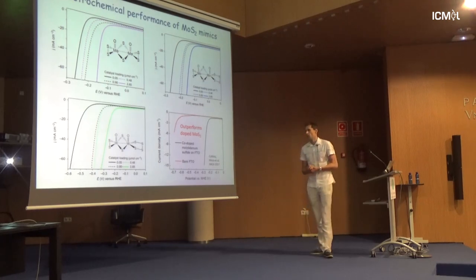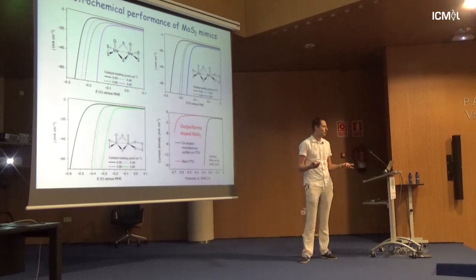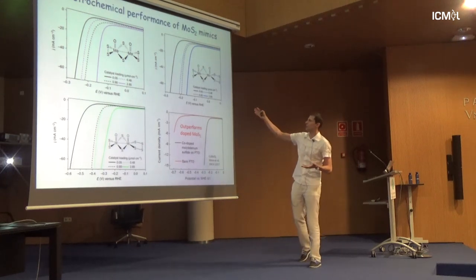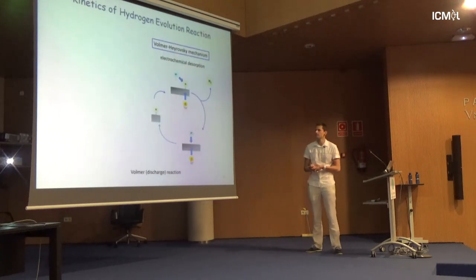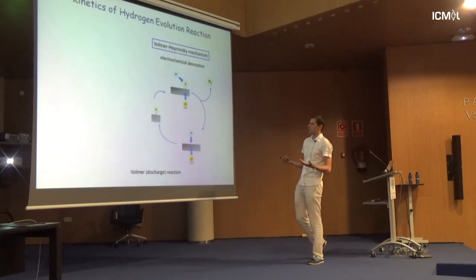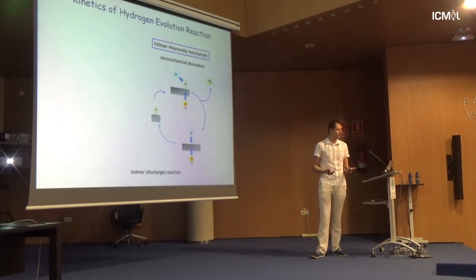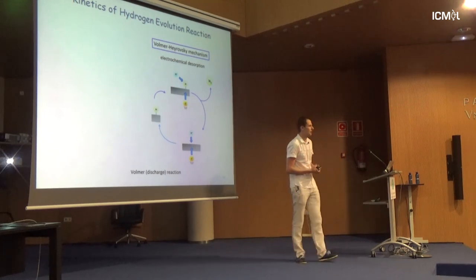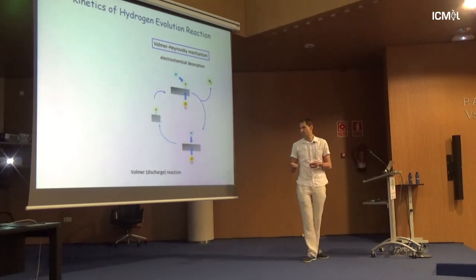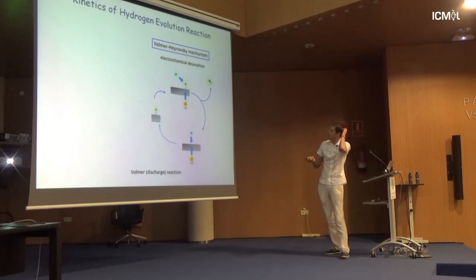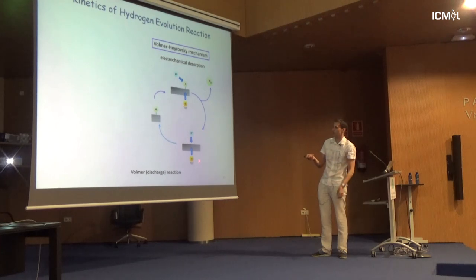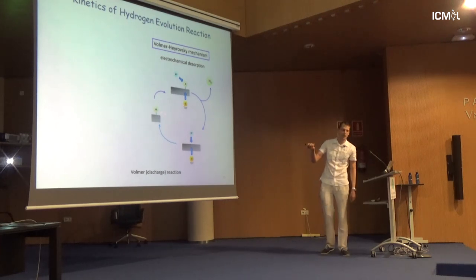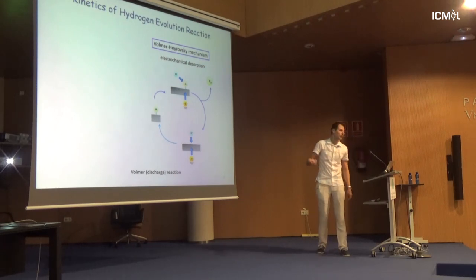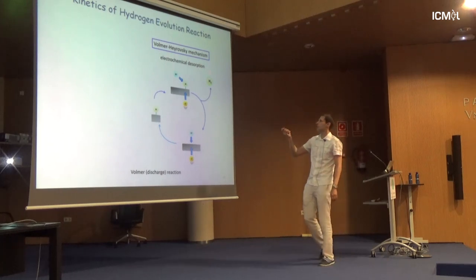So we substantially improve, and it's very easy to make. It's a molecular material, so you precipitate it on the surface. But for me, what was exciting was not just another very good electrocatalyst, but this phenomenon of why they behave exactly the same. There are a lot of theoretical calculations that you can do on this, and we started working with Carl Bohr. It's just to give you a rough idea of what's happening during hydrogen evolution. First you give an electron to a proton, and the proton gets adsorbed on the surface. Then with an extra electron donation, it can recombine the proton with hydrogen, and you have hydrogen evolution. This is called the Volmer-Heyrovsky mechanism.